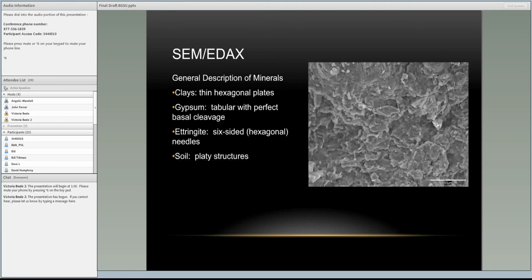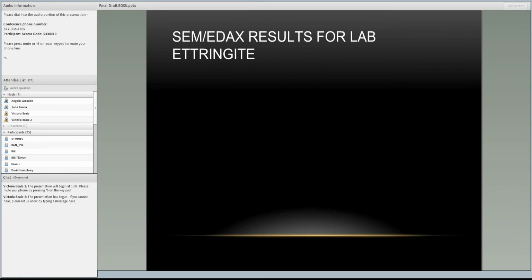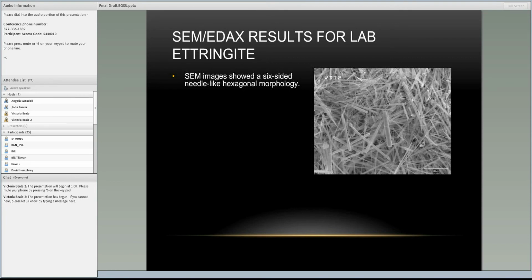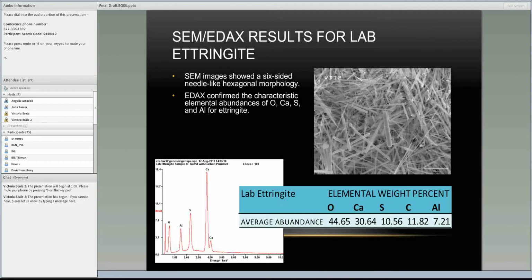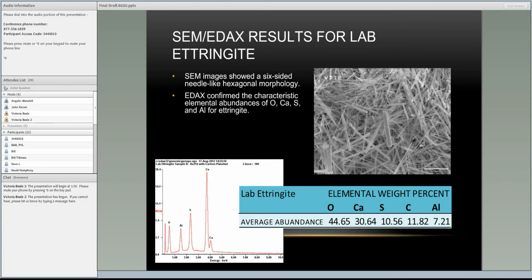So now we're back to our lab ettringite, and we looked at the sample with the SEM, and this is what it looked like. We did see the six-sided needle-like hexagonal morphology. Here in the lower left, you can see an EDAX spectrum, with the peaks for oxygen, aluminum, sulfur, and the high amount of calcium. Over here, I did several samples, so this is an average of all my samples of the elemental weight percents. With ettringite, you're always going to have very high oxygen and calcium, along with sulfur and aluminum. The carbon is from the carbon planchet and from carbon coating the specimen.